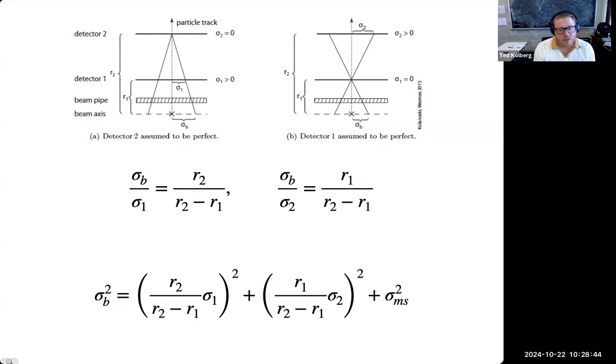So already with this simple expression, I think there's a couple of conclusions that you can draw about how your vertex detector should look. First, the resolution of detector 1 is always going to be more important than detector 2 due to the coefficients being proportional to the radii. By definition, R2 is larger than R1, otherwise they would be reversed. And that means that this coefficient shares the same denominator with this coefficient here, and the impact of the resolution of detector 1 is always going to be larger because R2 is larger than R1, and these ratios are otherwise the same. So that means if I'm going to pour money and engineering effort into shrinking my detector channels, I had better put that effort into the layer which is closest to the beamline, which I think makes intuitive sense, but it's nice to have a model that shows exactly quantitatively how that dependence might go.